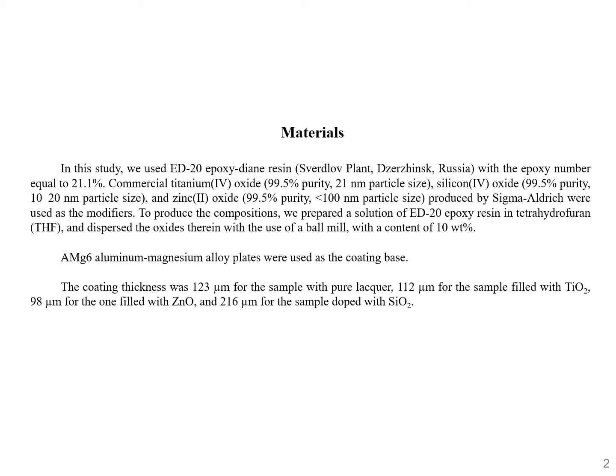In this study, we used ED20 epoxy-diane resin. Commercial titanium, silicon, and zinc oxides were used as modifiers. To produce the compositions, we prepared a solution of epoxy resin in tetrahydrofuran and dispersed the oxides there with the use of a ball mill with a content of 10 wt%. Aluminum magnesium alloy plates were used as a coating base.